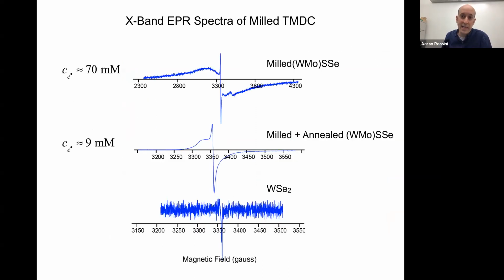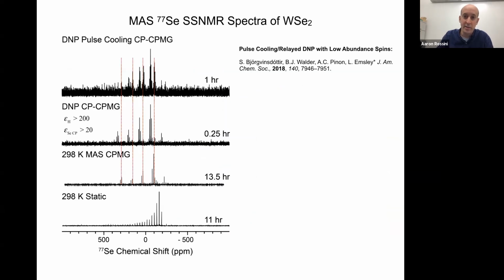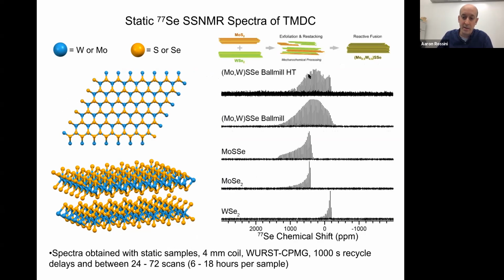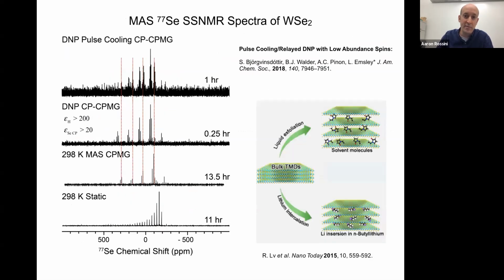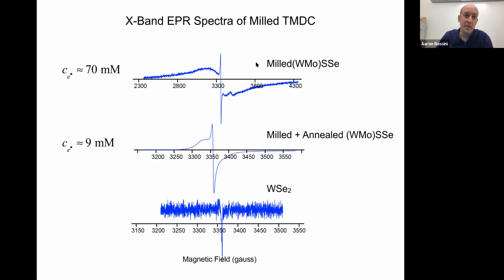Now, coming to the mixed samples, we actually wanted to get the magic angle spinning spectra of these mixed samples. Unfortunately, when we try and do both room temperature magic angle spinning with CPMG detection or DNP, we can't get any spectra. The reason is that the milled samples appear to have high concentrations of unpaired electrons, and these are likely a result of the mechanochemical milling breaking chemical bonds and leading to dangling bonds, so you have unpaired electrons that become part of the sheets.